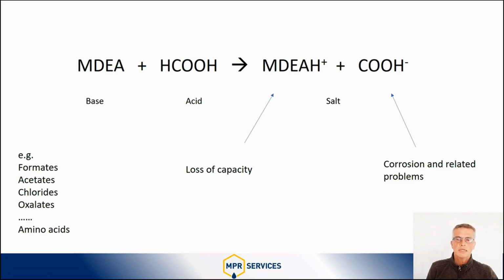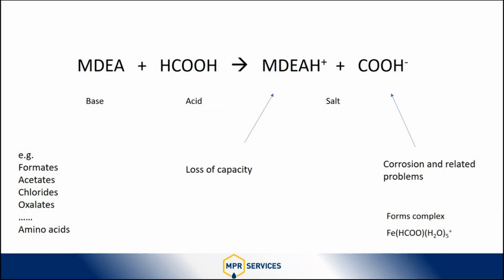You see, this is a simple equation. It shows you the two main problems. The amine forms a salt. It is protonated and it is no longer available to pick up gas in the absorber. The stripper cannot revert this reaction. But by reclaiming you can make the amine available again. But equally important, maybe more important I would say, you get rid of the heat stable salt anions, which contribute to corrosion.